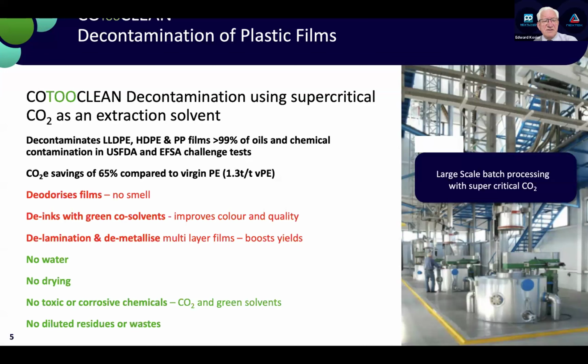The process can also delaminate and demetallize multi-layer films. This is another big opportunity for a process like this, where it can potentially unravel the more complex materials that have been used in the system. This process doesn't use water, which is often a big feature of conventional recycling, so that means we have lower costs of operation. We also have no need for drying, which removes a big energy component in film recycling.